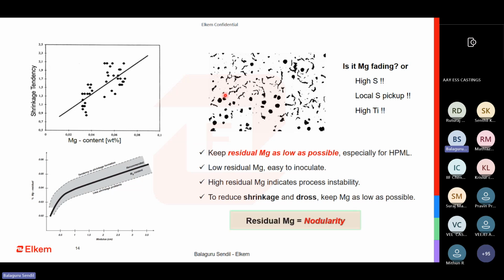So the residual magnesium, what do we measure? The residual magnesium has to be directly correlated to nodularity. Nodularity is nothing but the effective measurement of how round a particular nodule is. The pointer image is a nice nodule, with a very nice round shape and a respectable size. Whereas for the one above it, the size is okay, but the shape cannot be considered a perfect round. It doesn't match the Feret diameter. This distortion in shape can be attributed to both inoculant as well as Mg fading.